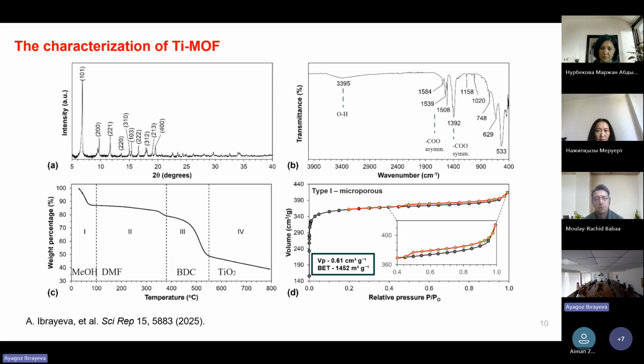To know the porosity of this material, we provided a porosimetry analysis. It gives us information that it is type 1 micropores, and BET was 1452, and pore volume 0.61.